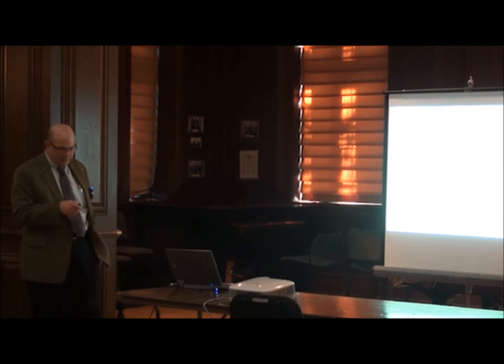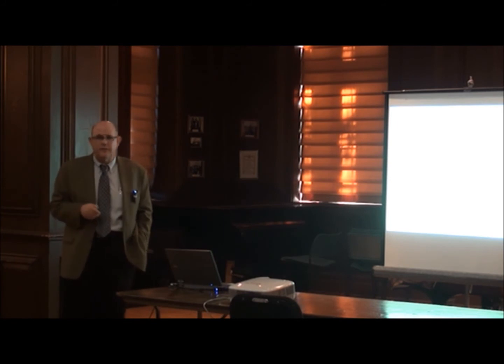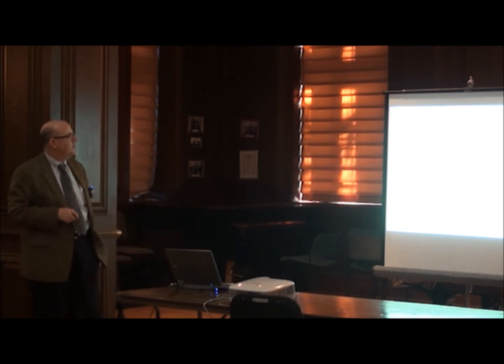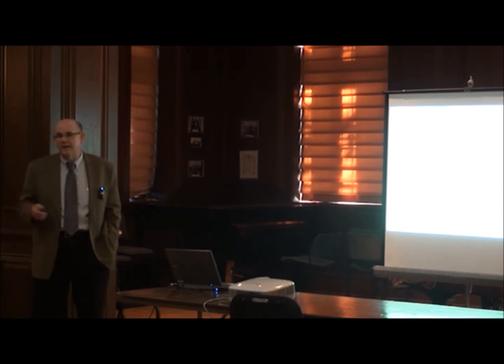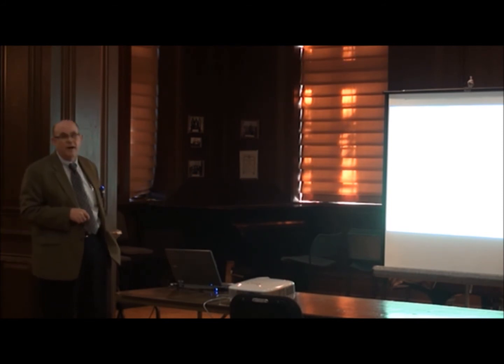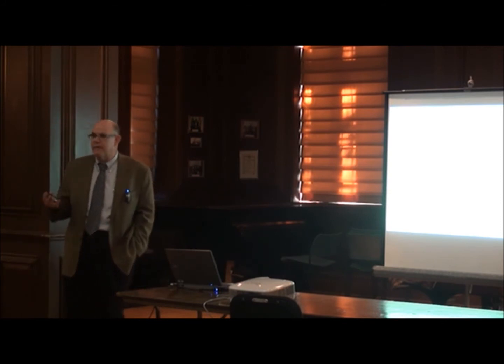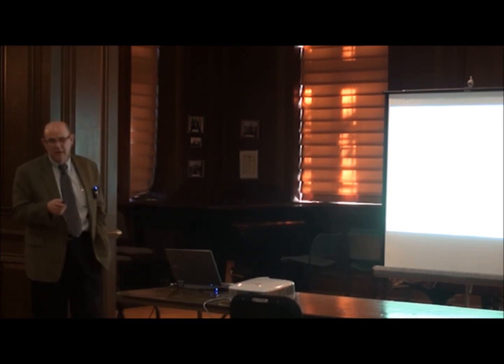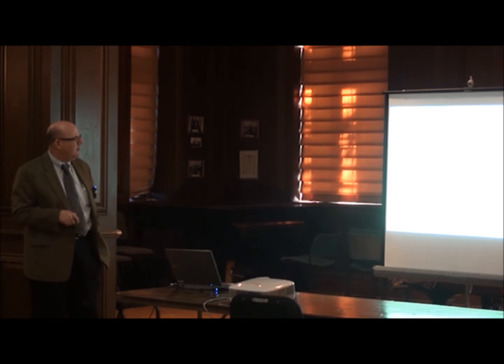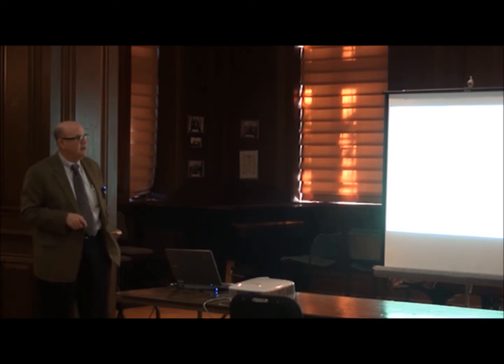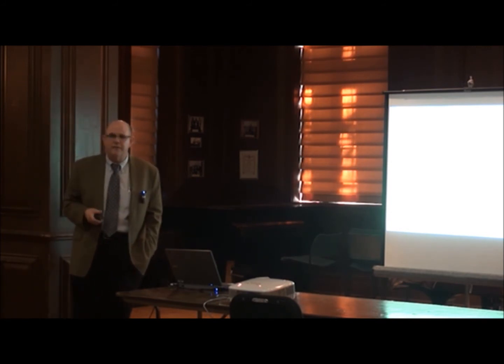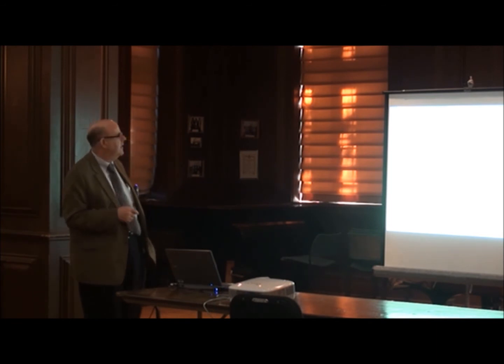We get to a point where the lambda ratio gets between 1 and 3. Now we actually have asperities touching across the interface. And if we get to the situation where lambda is much less than 1, we get to basically a dry sliding condition if there's no lubricants, and we get a real high friction coefficient. Or if we can at least get some of the lubricants to adhere to the surface, we're in the mode of what's called boundary lubrication. So we're going through these different regimes of lubrication relative to the surface roughness of the surface. And that's kind of the challenge.